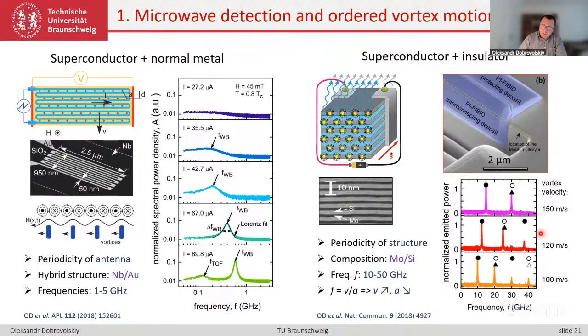Again, the experimental observable was just microwave power detected with a coaxial loop antenna placed in the vicinity of this multilayer system, with frequencies in the tens of gigahertz range. But so far, these effects were observed for vortex velocities in the sub-kilometer per second range. So the coherence was good, but the vortex velocities were not yet enough to think about their combination with the excitation of spin waves, because we first need to approach and touch the dispersion characteristic above the ferromagnetic resonance frequency.